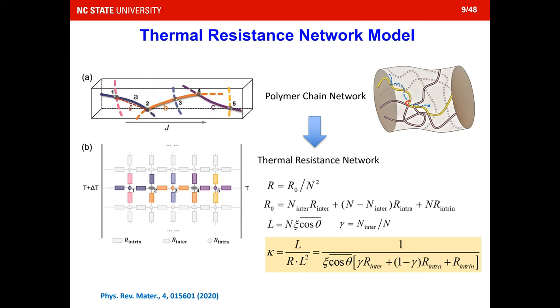But here we're trying to use this model to describe something that happens at a molecular level and see whether it still can work. We basically proposed a model using the polymer chain network and thinking about intra-chain and inter-chain conduction. And we realized that in polymers, you have a lot of one-dimensional chains, very long chains, and a lot of inter-chain transfer. So equivalently, topologically, this is actually a two-dimensional network. So if you write out the thermal resistance network model and then apply it to different scenarios, let's see what happens.